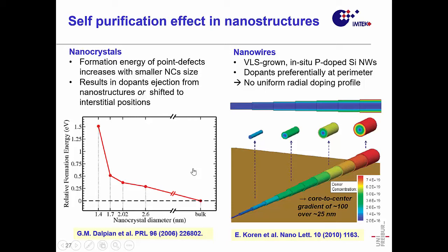It could be that the formation energy of these point defects, of putting these dopants into a lattice position for these small objects, is increasing. You see it here in some calculations for nanocrystals. And if you do this doping, which is very often done in literature for the nanowires, you are also changing something. So how to dope a nanowire during the growth?